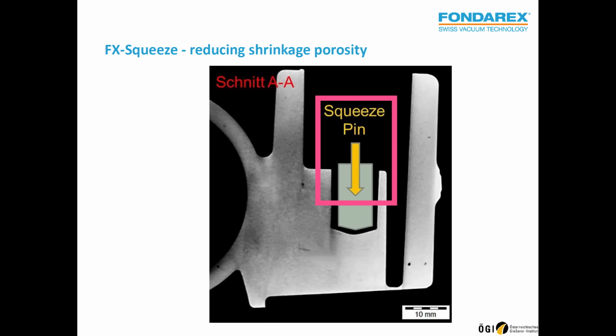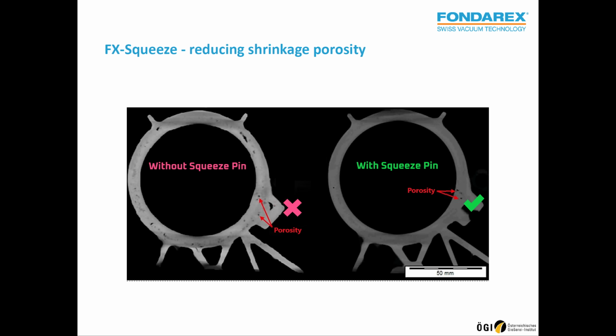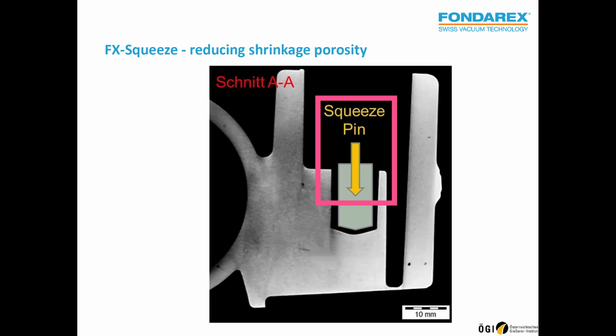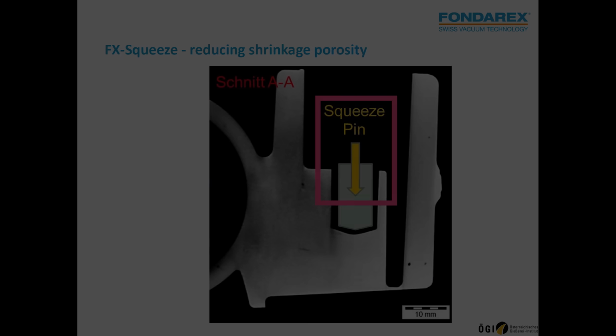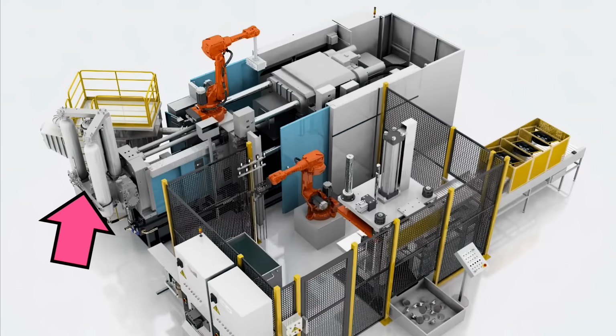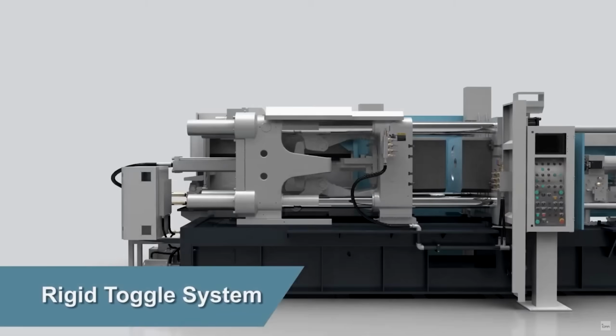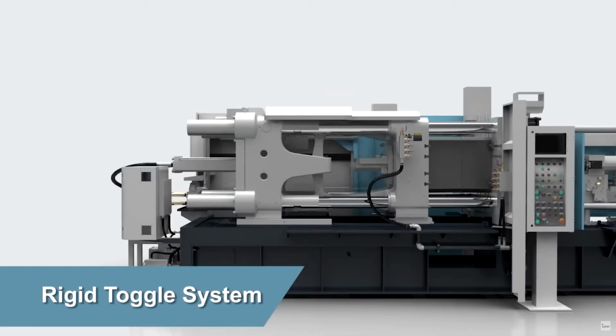High-pressure die casting machines sometimes use pins within the die that actuate when the molten metal is injected. Those pins compress or squeeze the molten metal in specific areas at specific times to help reduce porosity due to shrinkage. However, the drawback is that those pins usually run off the hydraulic pressure accumulators that are built into the die casting machine, which are used to squeeze the massive die together.